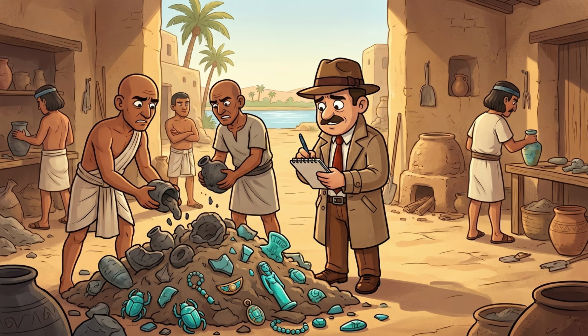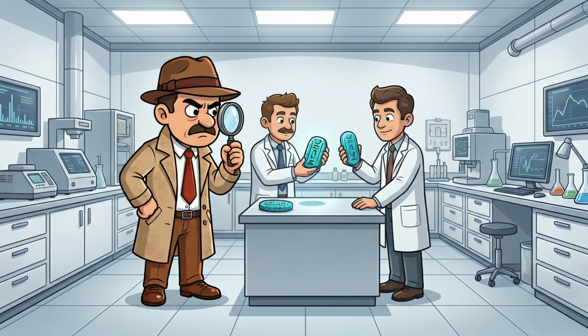Too little heat, and the surface remained dull. Too much heat, and the shape could deform. Too much copper, and the color darkened. Too little, and the sacred blue faded toward lifeless gray. Modern laboratories can reproduce Egyptian faience in broad terms, but recreating the exact appearance, texture, surface depth, and workshop consistency of ancient examples remains difficult.